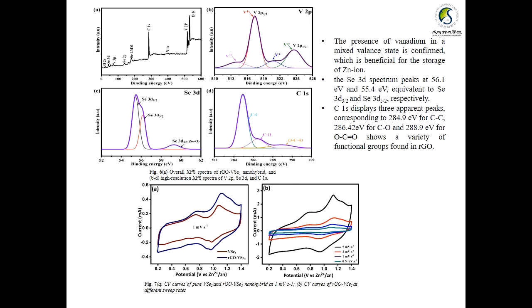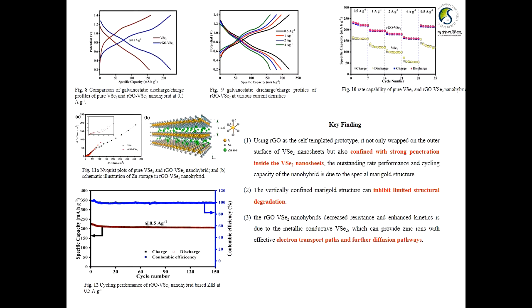You can see that the reduced graphene oxide and VSe2 hybrid shows more predominant peaks when compared to the pure material. Further we fixed the hybrid material and varied the current rate, like 0.5, 1, 2, 5, and it shows an increase. This comparison of galvanostatic charge discharge profiles of the pure material and hybrid material shows that my hybrid material has an extreme capacity compared to the pure material, with a stabilized rate capability performance and 91 percent capacity retention for a long cycle of 150 cycles at 0.5 ampere per gram.